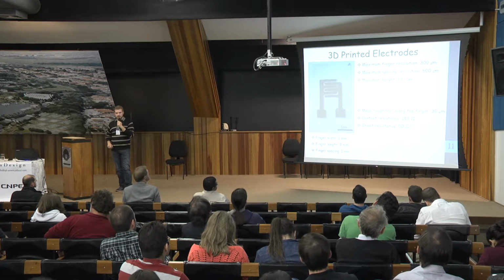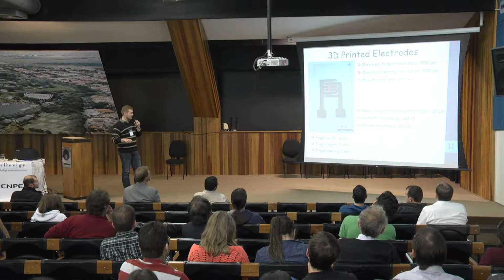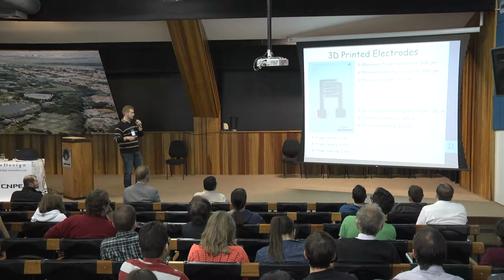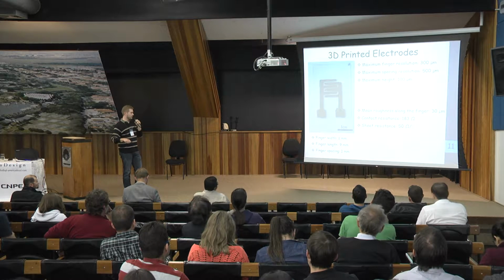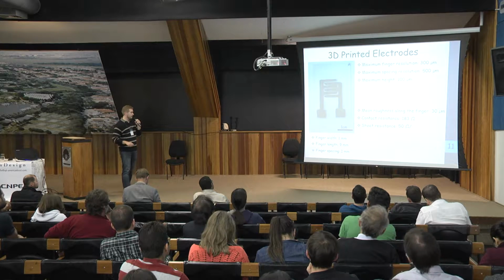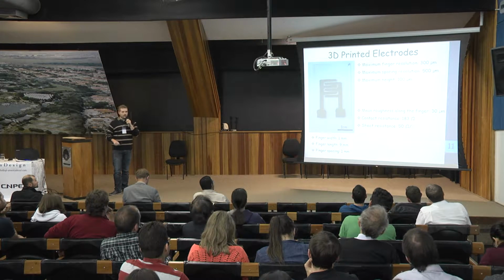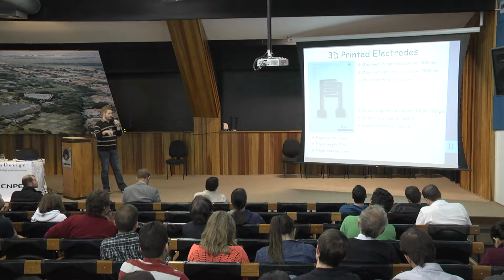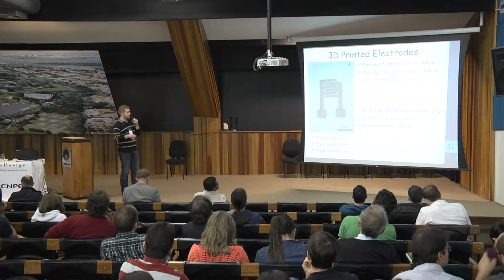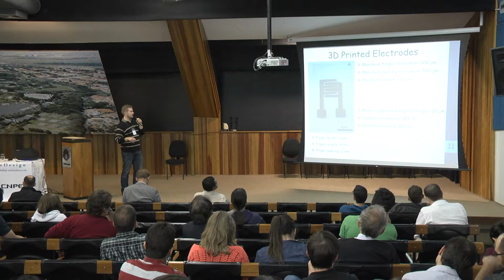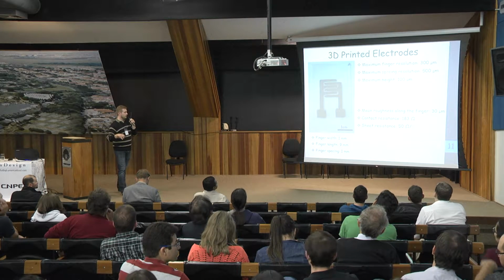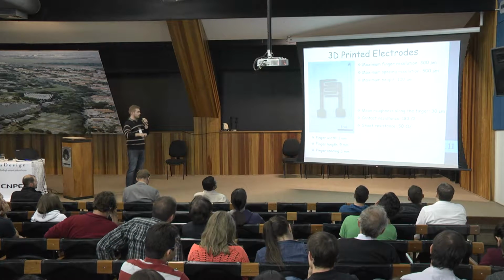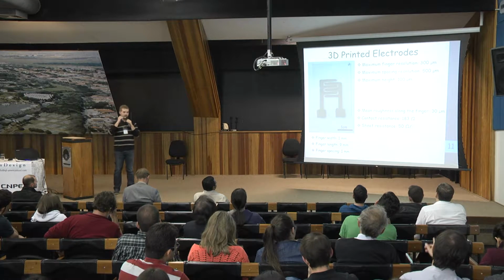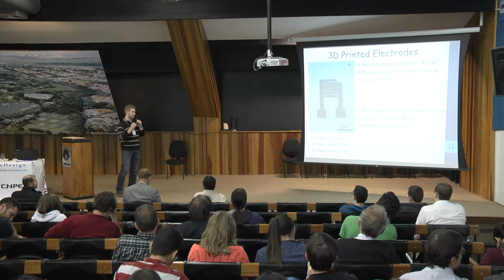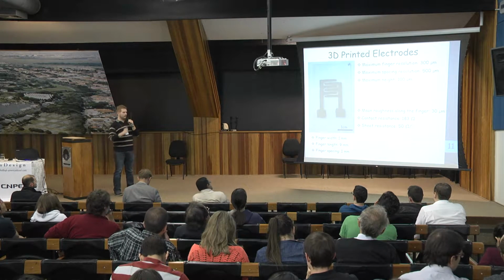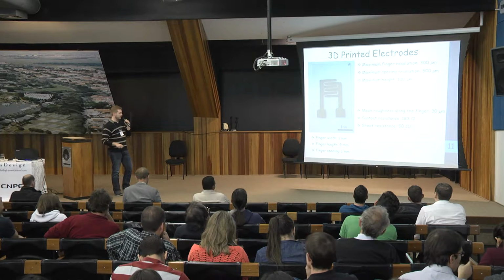So we start with some rough geometries. We start with IDEs, really rough now, with finger widths of 1 millimeter and finger spacing of 1 millimeter. And working on the 3D printer parameters, we could get better resolution, to a minimum finger width of 300 microns and a minimum spacing of 500 microns. This limit is attached to the 3D printer, so we could get a Z resolution of the printer of 100 microns.